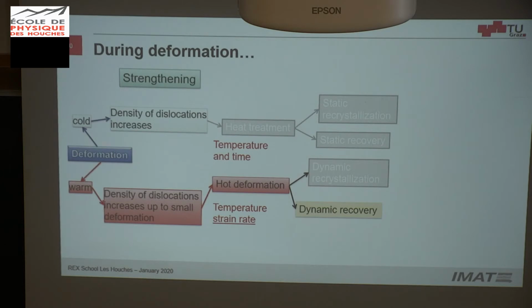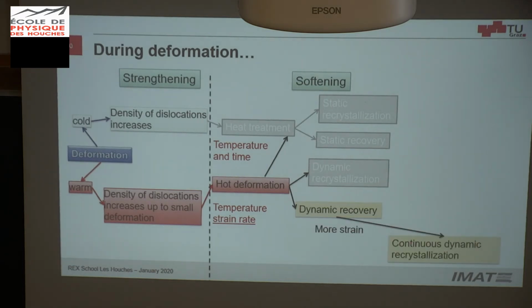So this is when we start deformation, then we have cold deformation, and the density of dislocations increases. This is not what I'm going to cover in this talk. When we have warm deformation, at the beginning the density of dislocations increases up to a small deformation. Then we may have either dynamic recrystallization or discontinuous dynamic recrystallization, like in nickel-based alloys, and dynamic recovery in our case. And if we go further with the strain, then we will have what is called continuous dynamic recrystallization or extended recovery, or many of the names that you can find in the literature.